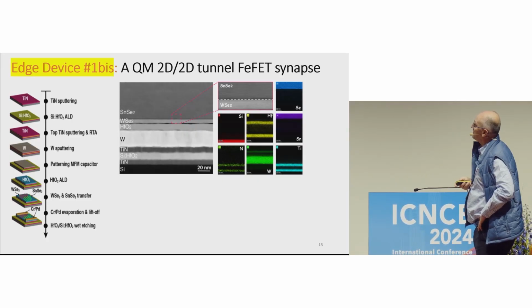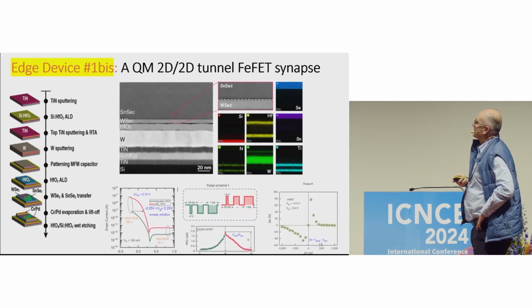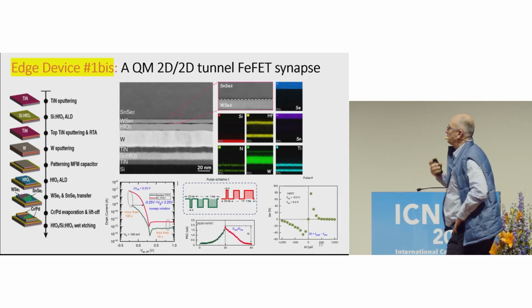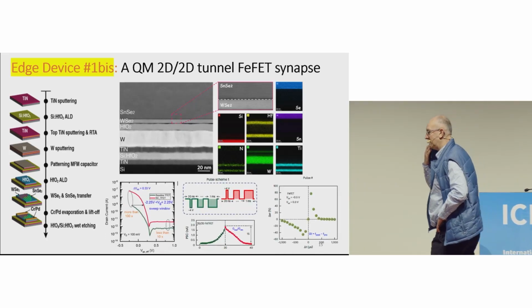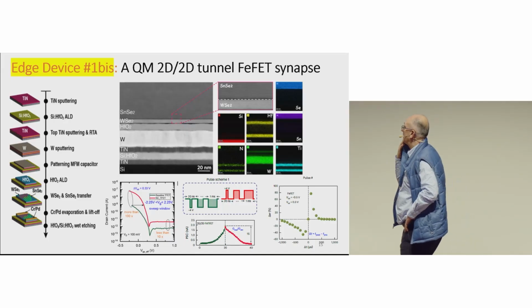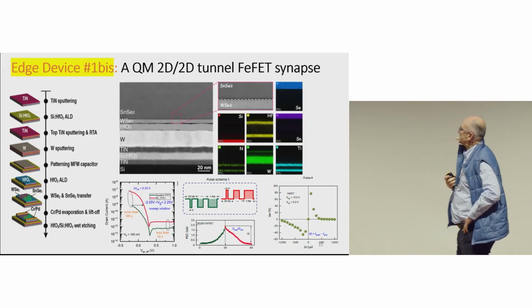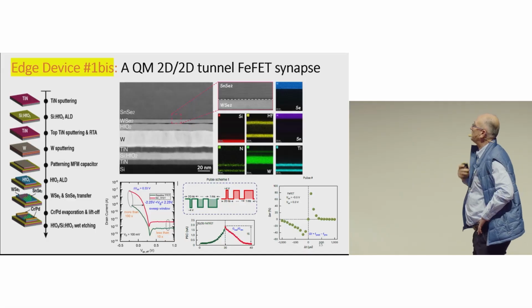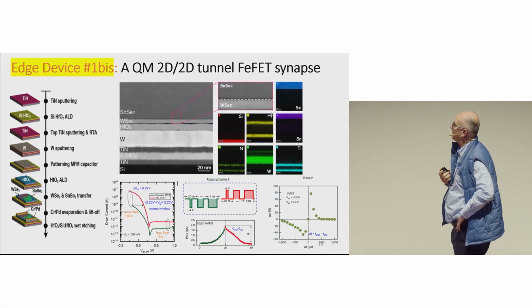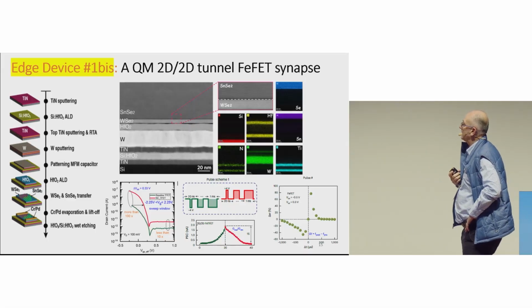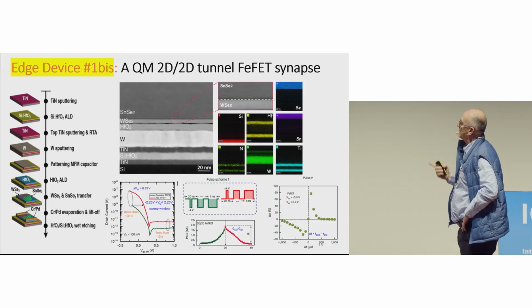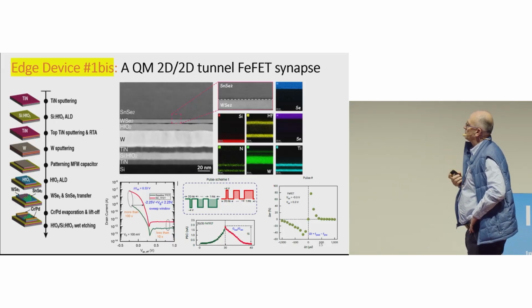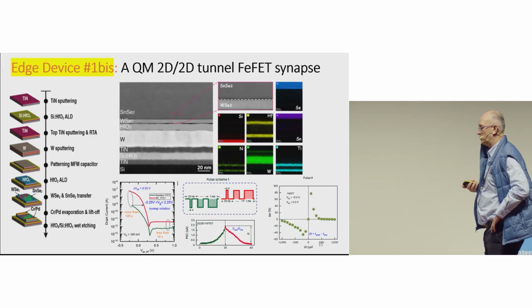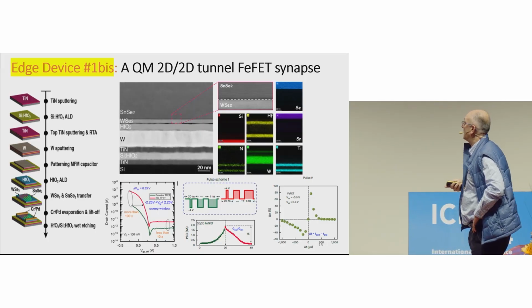So this again was very carefully checked, was nicely transferred, and I want to give you just an idea: when you do this ferroelectric gating of such a tunnel FET, you may get even something like a negative capacitance effect. You see the red characteristic is the characteristic with ferro gating in one sweep of the curve. So practically you are boosting the performance of the tunneling FET with this type of gate stack.